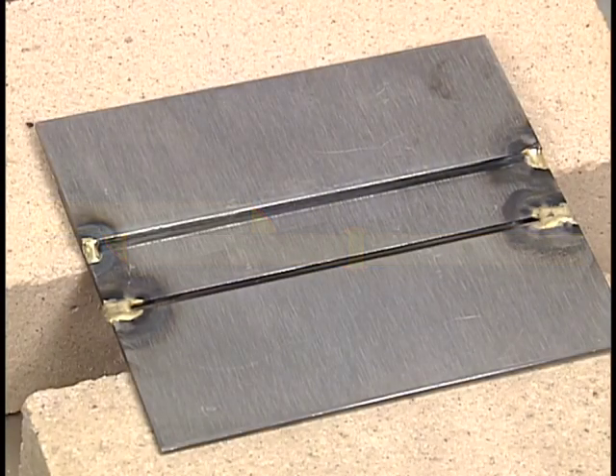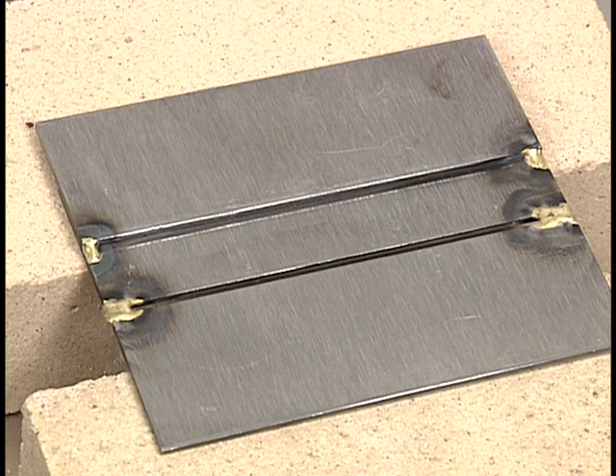The butt joint consists of a square groove weld made up of 1 layer, a root pass, deposited using the braze welding technique. The workpiece for this exercise consists of 3 pieces of 11 gauge mild steel plate. The plates are tack welded to form a square groove butt joint and placed in the flat or 1G position. A lap joint is formed when another plate is tack welded to the workpiece and placed in the horizontal position or 2F position.